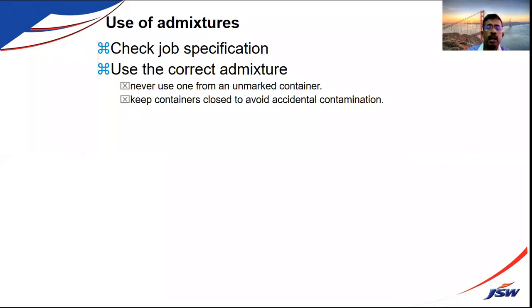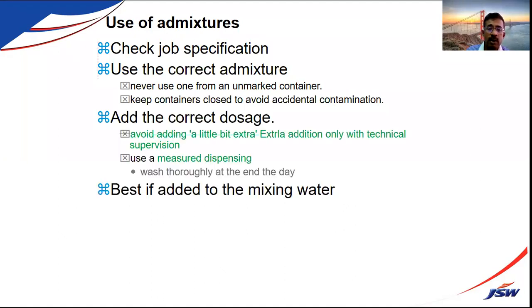So coming to the admixtures, check the job specification. For what purpose the concrete is being used, whether it's a waterproofing concrete, whether it is a mass concreting application, whether it is a roof slab, whether you are doing the concrete in the open area where the wind velocity is more, it sucks away the water when you place the concrete. So these are very important things when you are making a concrete. That's why I'm talking about 7 steps in concrete. Adding the mixing water is very important. The dosage of water, how much you have to add, what is the percentage of water cement ratio.